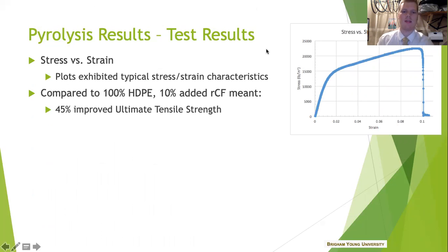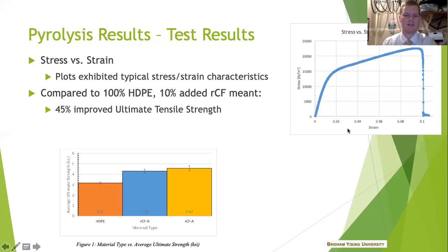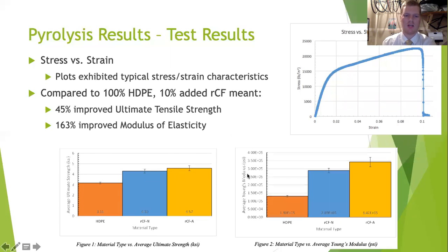Adding 10% recycled carbon fiber to the HDPE meant some pretty big changes. Here you can see the ultimate strength with a figure of 4.57 KSI for the recycled carbon fiber in ambient conditions as compared to 3.16 KSI with the HDPE. Pretty big change. As well, the modulus was even more significant. So with that ambient carbon fiber, we saw a marked increase from the HDPE baseline.